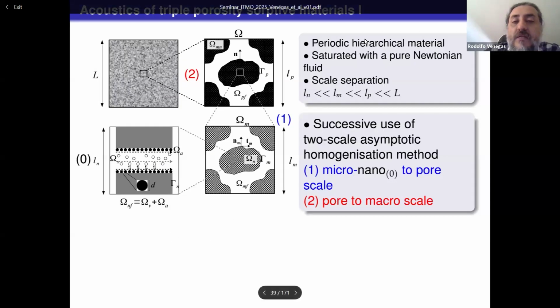So what we do is consider again a periodic hierarchical material, and there's scale separation. This is on the order of 1 nanometer, this is on the order of 1 micrometer, this is on the order of 1 millimeter. So this is 1,000 times larger than this, and this is 1,000 times larger than that. We consider long wavelength wave propagation and apply homogenization from this scale to get a representation of what's happening in the grains themselves.